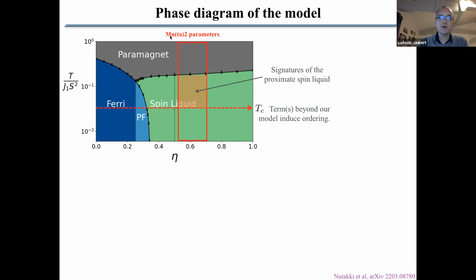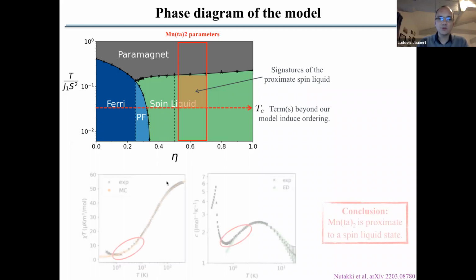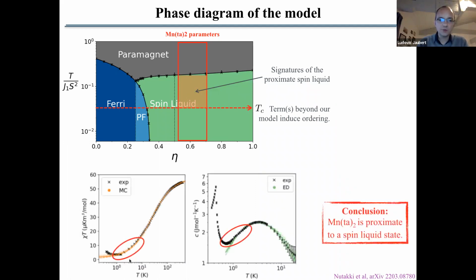So for manganese MnTa2 parameters, classical Monte Carlo simulations find no long range order. In experiments, we have it at very low temperature, so we cannot describe the very low temperature physics of MnTa2. But at intermediate temperature, in this temperature regime here, we can expect to see the proximity of a spin liquid state in MnTa2. So this regime here will correspond to a classical spin liquid.